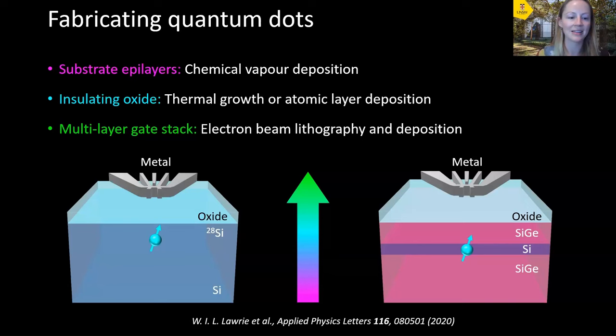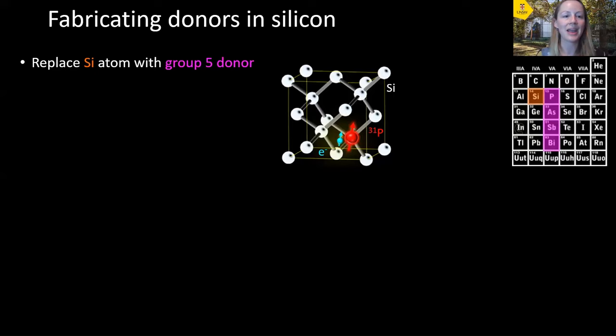So now let's talk about how we can fabricate donors in silicon, which is the platform that I research in. For donors in silicon, we don't require any surface nanoelectronics to confine our electron spins like we do for the quantum dots previously. Instead, when you replace a single silicon atom, which is found in group 4 of the periodic table, with any of the group 5 donor atoms, it binds an extra electron with the Coulomb potential of its nucleus, because the donor nucleus has an extra positive charge relative to the silicon surrounding it. So we don't need any extra gates to confine our electron. It just naturally sits at the donor nucleus.